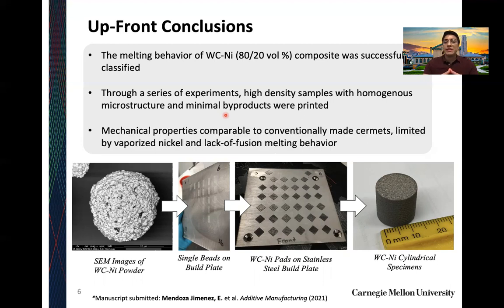And finally, we tested the hardness and we found it to be comparable to conventionally made cermets. And it was only limited by the vaporized nickel and lack of fusion melting behavior, both of which are defect mechanisms that are actually present for metal 3D printing in the same process. So that's very indicative that we can actually use this material system, and this material system behaves similar to a pure metal.